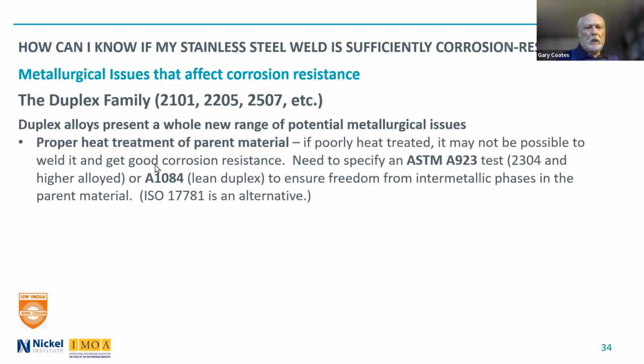So with duplex alloys, again, the proper heat treatment of the parent material is extremely important. If it's poorly heat treated, it may not be possible to weld it with good corrosion resistance in the weldment, in both the heat affected zone and the weld metal itself. And so therefore you need to do tests, and that's shown in ASTM A923 for the duplex grades 2304 and higher, or A1084 for the lean duplexes. And that ensures that there's freedom of intermetallic phases in the parent material.